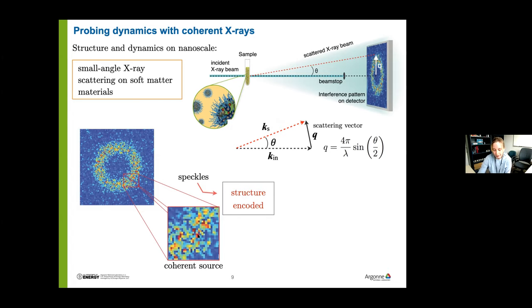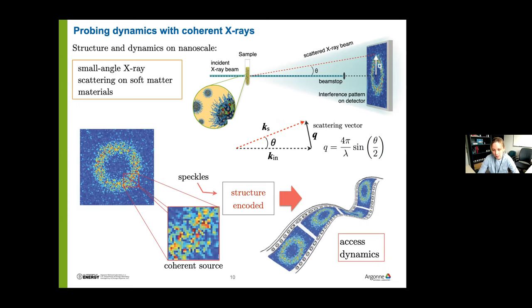If we use a coherent X-ray beam, that scattering pattern consists of a grainy structure called a speckle pattern. The position and structure of that speckle pattern relates to the positions of the particles in real space. It is hard to extract the exact structure; however, if we imagine that the real structure is changing in time — like particles moving in water — then the diffraction pattern will also mimic that dynamics.